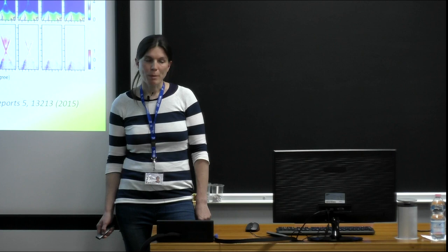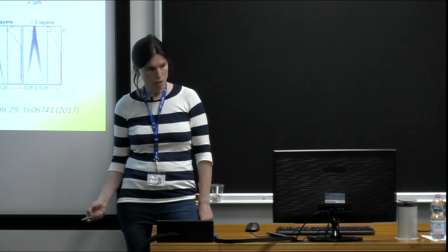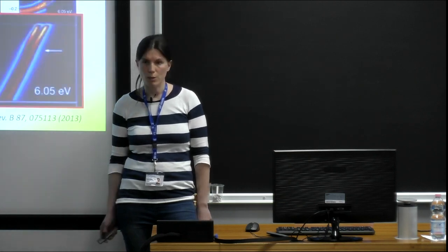Can one say that there is a band crossing if the observed band gap is 1 to 10 millielectron volt? It depends on the resolution of your system normally. There are some dedicated beamlines that study at very high resolution. You have to go to very low temperature probably. You have to increase your resolution by several times. Probably with laser-based techniques, you can effectively do this.